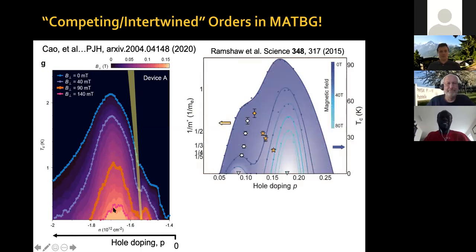This is again very reminiscent of data in the cuprates. This is a paper by Brad Ramshaw, where they measure TC as a function of hole doping and magnetic field. At some point, you can see they split the superconducting dome into two domes, and then only one of them remains. Of course, the difference between this and this is that the continuous lines that you see are guides to the eye. In reality, there are only a few dots, as you can see here, whereas this is actually a continuous measurement.